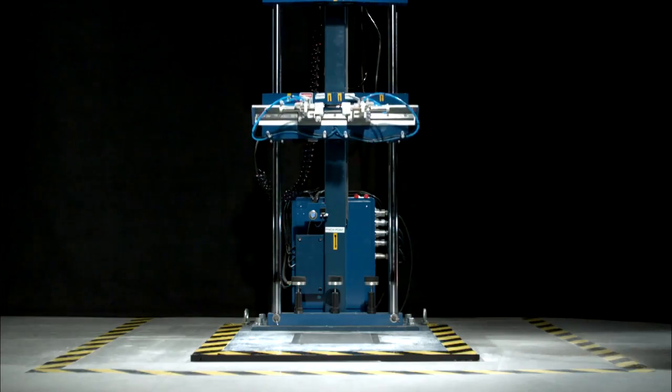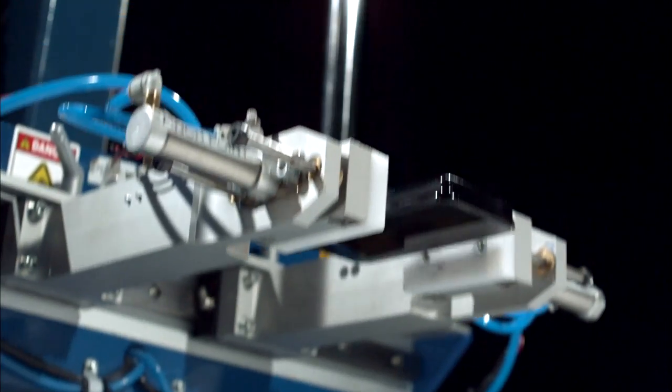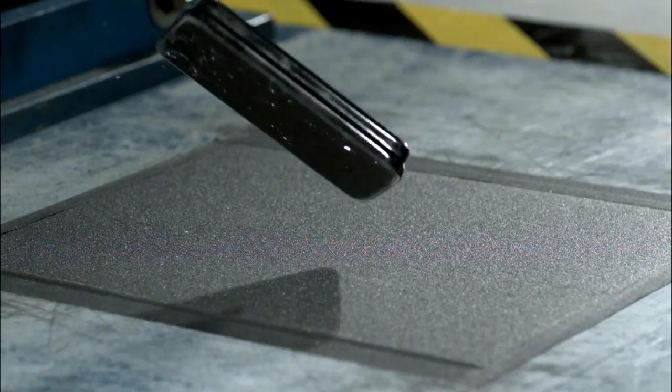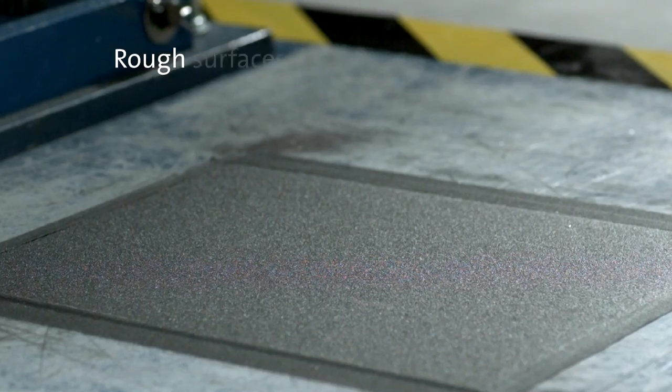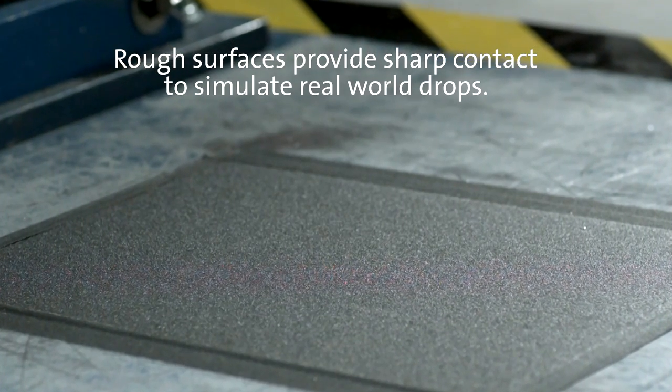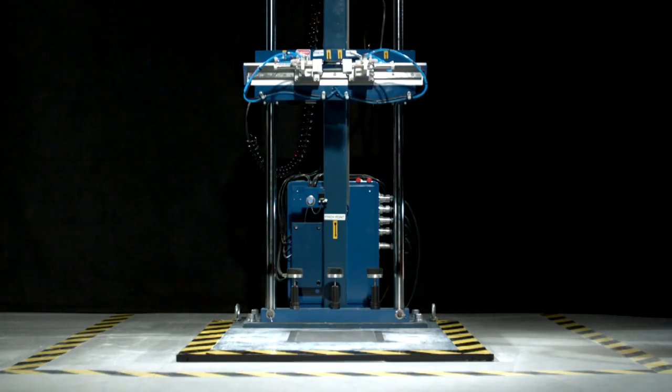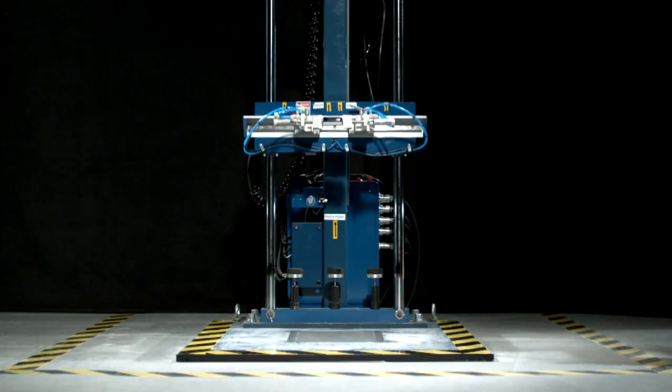Microscopically examining cover glass broken during our tests, as well as actual field failures, we analyzed flaw sizes responsible for the failures. That analysis told us that a specific grid of sandpaper could be used to best approximate the field's rough landing surfaces in our drop test machine.